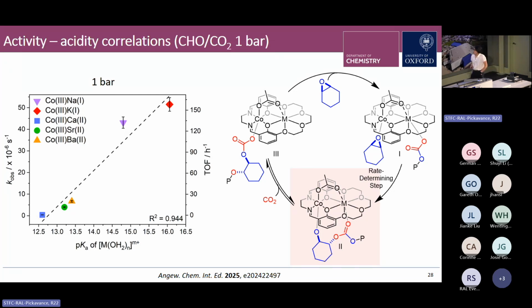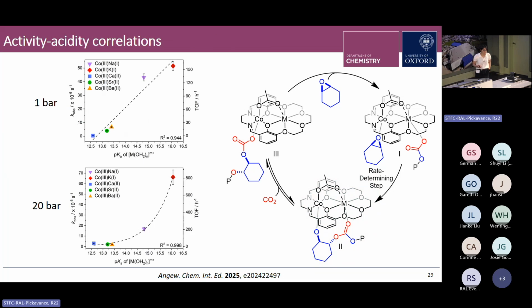So tentatively, we propose that you can gain some insight into the relative balance of the key intermediates in the catalytic cycle from performing this structure activity investigation at different carbon dioxide pressures, where at 20 bar CO2 pressure, our key rate determining intermediate is this carbonate species, which gives rise to a nonlinear trend, whereas at reduced CO2 pressure, our alkoxide becomes more important, and we see that by the fact that the activity-acidity correlation is now linear. But this hypothesis is quite early stage at the moment and requires further substantiation, and that's the topic of ongoing work in our group at the moment.